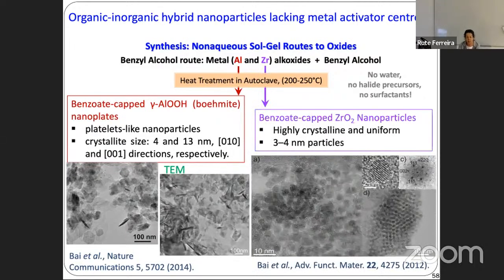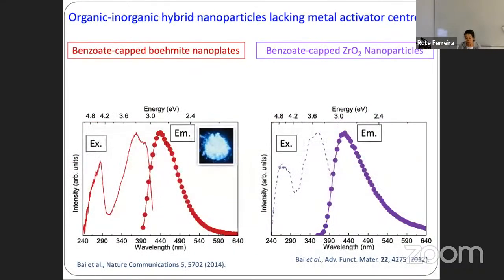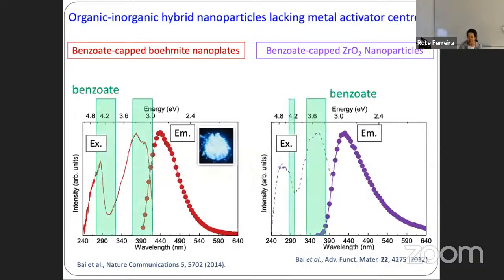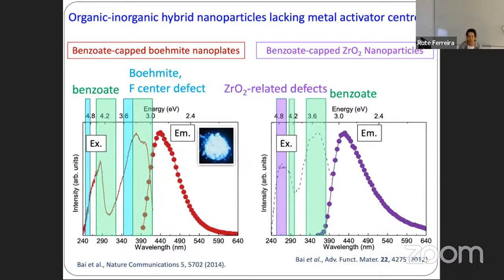Whereas the benzoate capped zirconium nanoparticles are highly crystalline and uniform and have an average size between 3 and 4 nanometers. If we focus on the emissions, on the photoluminescence properties, we can see in the excitation spectra of both nanoparticles the contribution of the excited states of the benzoate groups. And for the case of the boehmite nanoparticles, we can see also the contribution of a defect that is very well known in the literature, the so-called F-center defect. Whereas in the case of zirconia, we have an oxygen-related defect that is responsible for an absorption in the high energy side, in the lower UV spectral range.